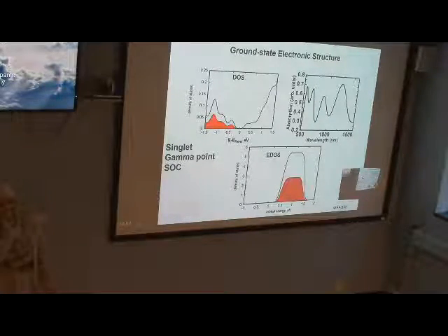It's different from your spectra, because the spectrum takes your excited DOS multiplied by what? Oscillator strength. Technically, if you multiply each of the states by oscillator strengths, you will get the absorption spectrum. If you do not include the weight with respect to the oscillator strengths, you will just get this EDOS.